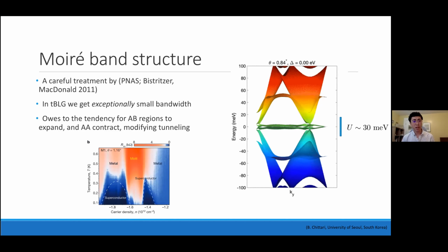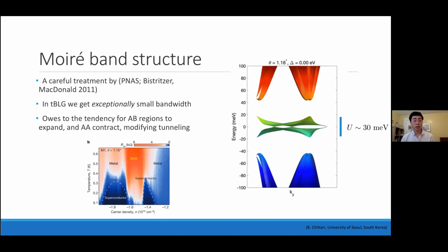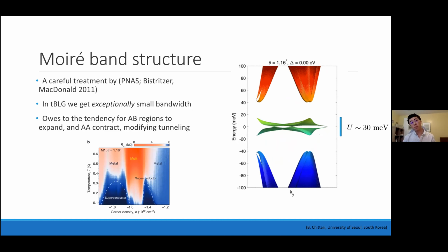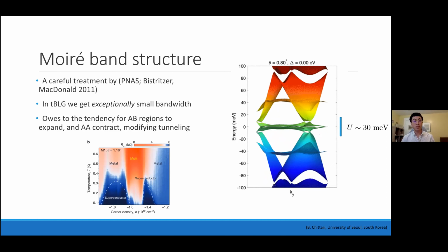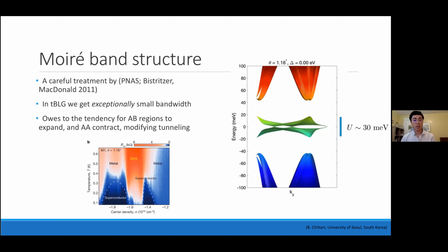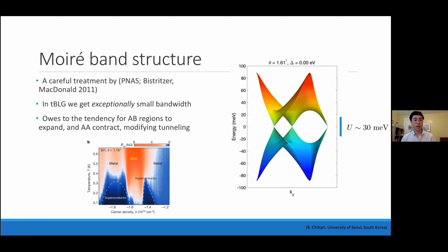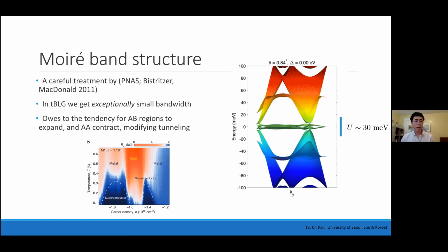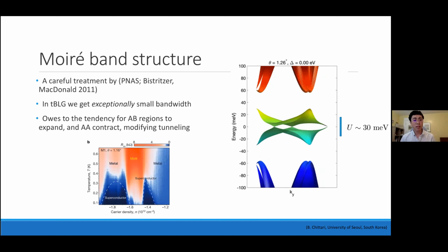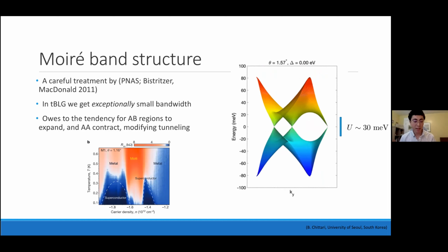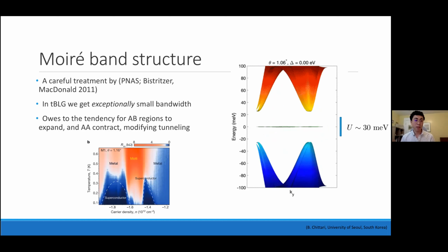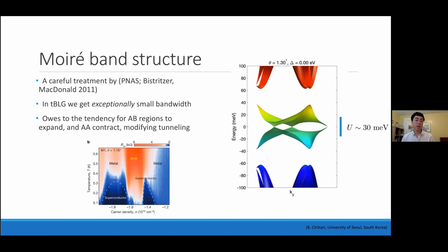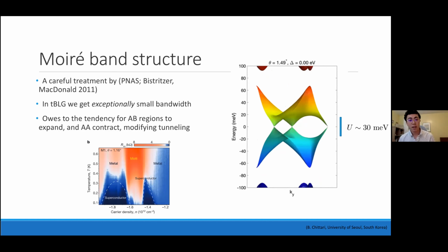And this wasn't just conjecture. In the end, it turned out to be a good prediction, not necessarily of particular correlated phase realizations, but it pointed our experiments in the right direction. And what we found in the case of twisted bilayer graphene in particular, in the Pablo Jarillo-Herrero group at MIT in 2019, was the observation of various glorious phases in twisted bilayer graphene. That included certain metallic behaviors and unexpected superconductivity, separated by insulators of an unknown origin.